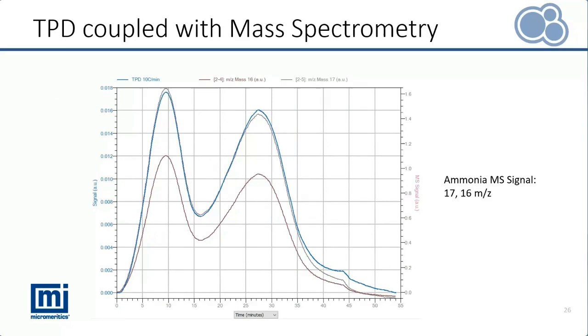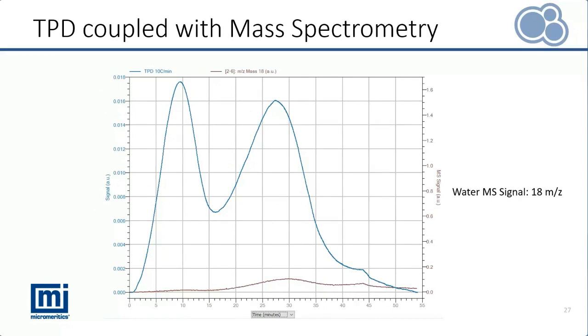I also had the benefit of monitoring the mass spec signals to verify the TCD data actually represents the quantity of ammonia desorbed. The mass-to-charge signals at m/z 17 and 16 nicely align with the TCD signal, also showing the expected relative intensities. Additionally, the water signal was monitored to verify if there was any interference from water on the TCD signal. No significant amount of water is present, with only a negligible amount of water desorbing with the second peak, possibly from the gas cylinder, residual system water, or incomplete removal of water bound to the strong acid sites. This confirms that the TCD signal nicely represents the quantity of ammonia desorbed.